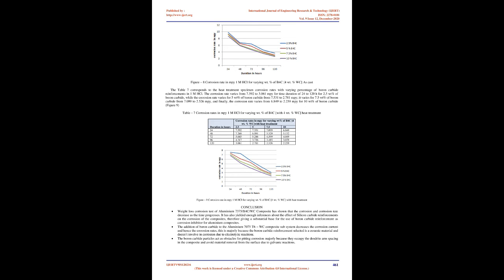Table 7 corresponds to the heat treated specimen corrosion rates with varying percentage of boron carbide reinforcements in 1 M alkaline solution, NaOH. The corrosion rate varies from 8.592 to 3.261 mpy for time duration of 24 to 120 h for 2.5 wt% of boron carbide, while the corrosion rate varies for 5 wt% of boron carbide from 8.351 to 2.981 mpy. It varies for 7.5 wt% of boron carbide from 8.099 to 2.726 mpy, and finally, the corrosion rate varies from 7.849 to 2.559 mpy for 10 wt% of boron carbide, Figure 7.